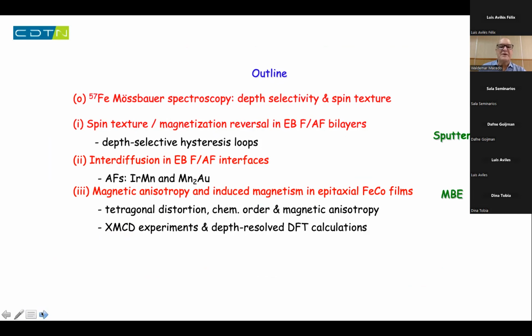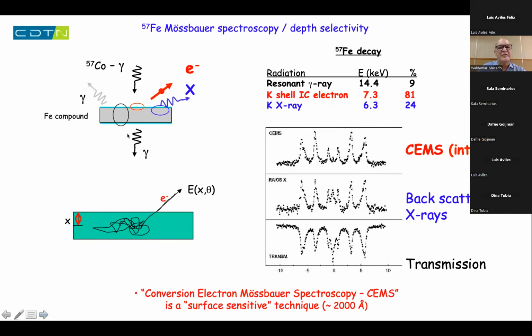Okay, about Mössbauer spectroscopy, this is when you have the Mössbauer effect. Of course, it's a gamma resonance, but in the decay after excitation, you can have electrons, X-rays, or gamma rays produced from the decay of the iron 57, and you can detect X-rays, gamma rays, or electrons. And if your sample is not homogeneous, you can probe different depths inside your material. That means if you are detecting electrons, you can say that conversion electron Mössbauer spectroscopy is a surface-sensitive technique, but surface means 2000 nanometers also, okay?